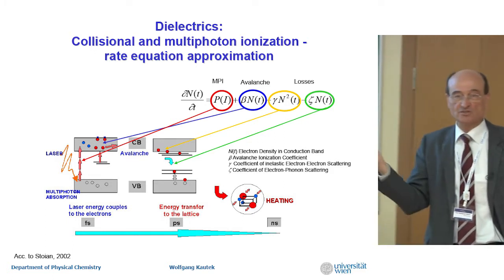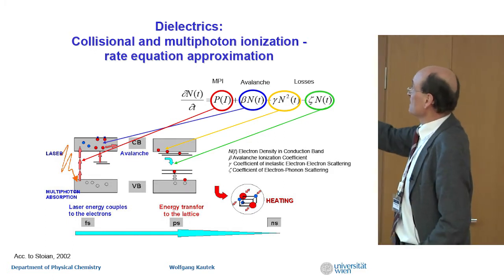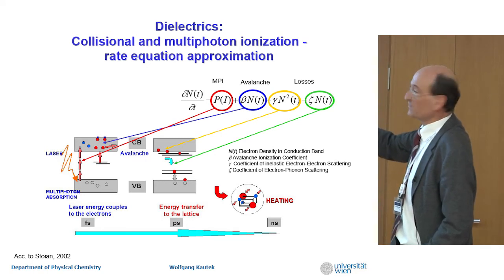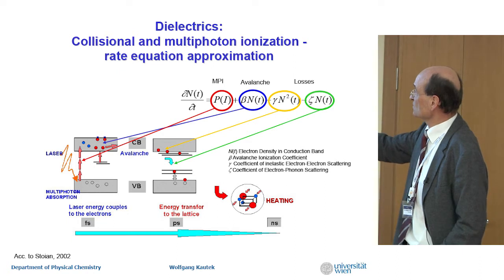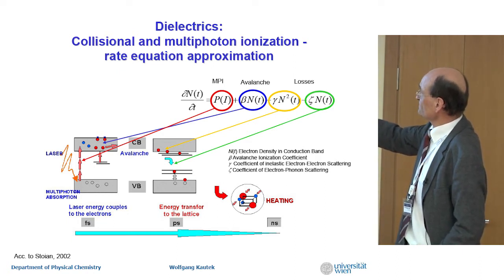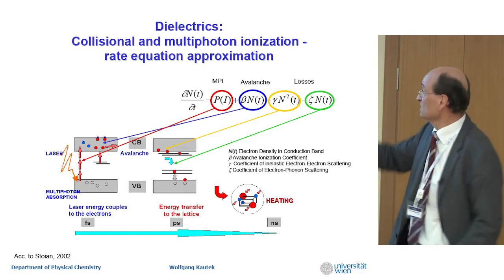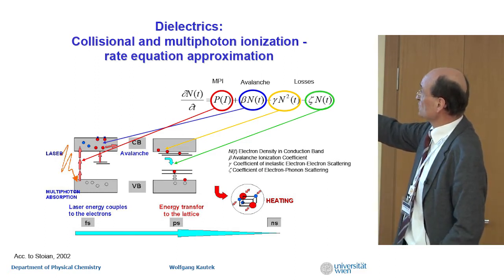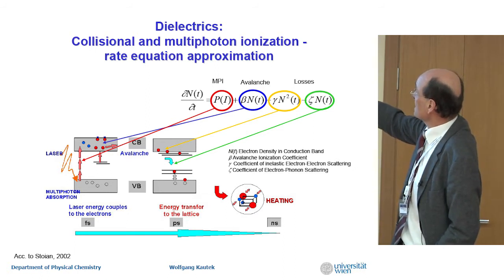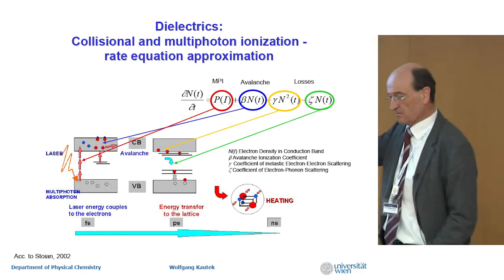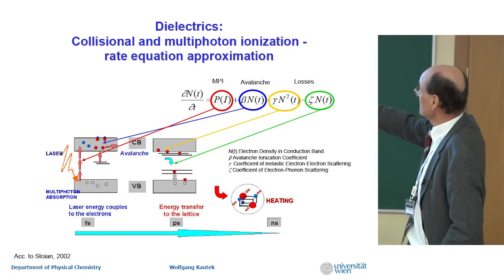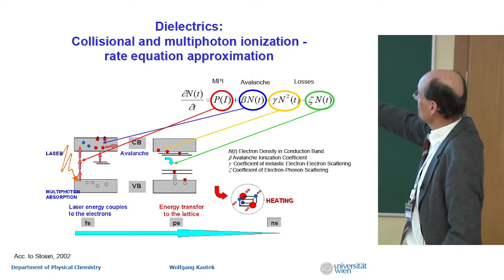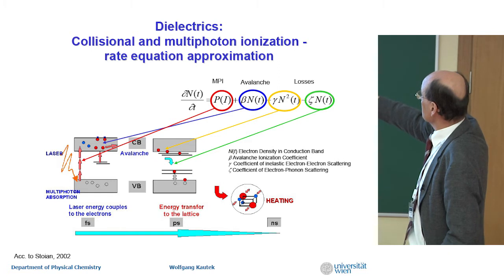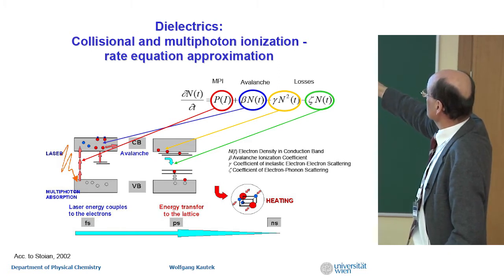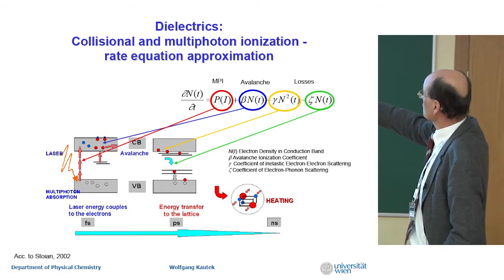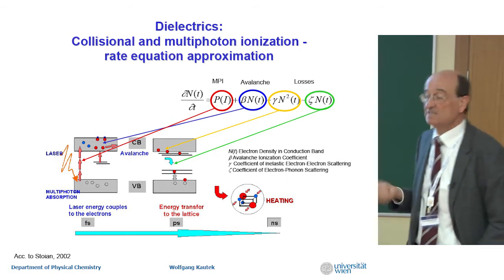And if we have too many free electrons, then the material may disintegrate. So that's the measure. And a positive contribution is the multi-photon excitation, short times. We have another possibility if we have defects, as I told you. They generate a couple of thermal electrons in the conduction band, and they can serve an avalanche process together with the free electron absorption. And then we have losses. One loss is, of course, the inelastic electron-electron scattering, and then finally the electron-phonon scattering, which heats the lattice.